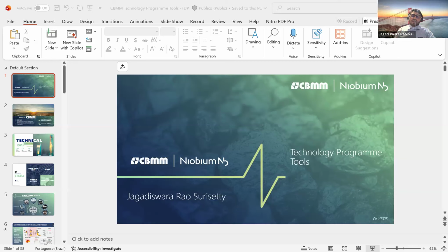It also has other features like niobium scan and through thickness analysis. Basically, we use through thickness analysis particularly when we are rolling thick sections. Thick sections means plates, where we roll, say, 50 millimeter or 25 millimeter. We need to understand the surface austenitic grain size, center austenitic grain size, as well as the quarter austenitic grain size. This information can also be provided by this tool, as well as the phase transformation tool.